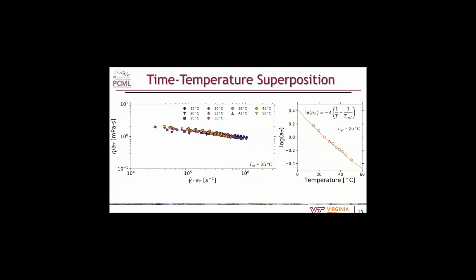We wanted to estimate larger shear rates, so we applied time temperature superposition to our materials. We used an Arrhenius equation to find multipliers that we could multiply against each temperature data set, against the shear rate, until they line up. Then we can match that with this Arrhenius equation to make sure everything jives well.